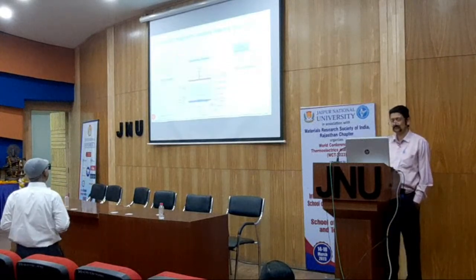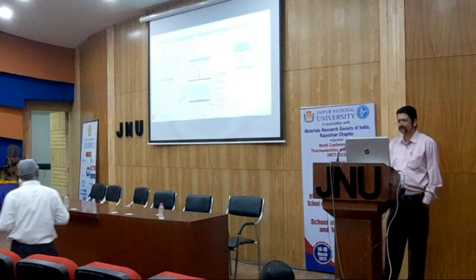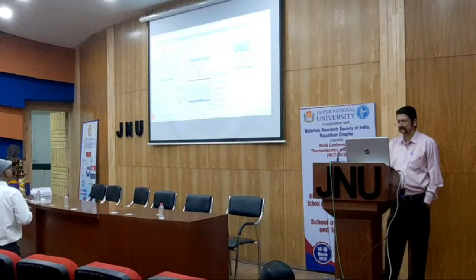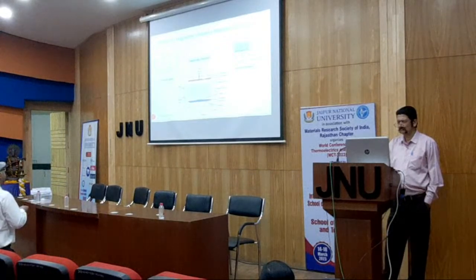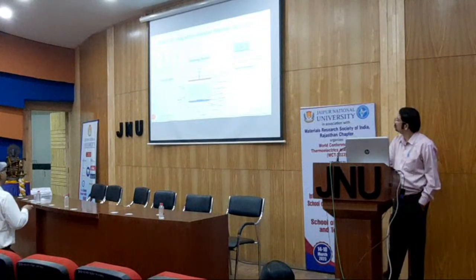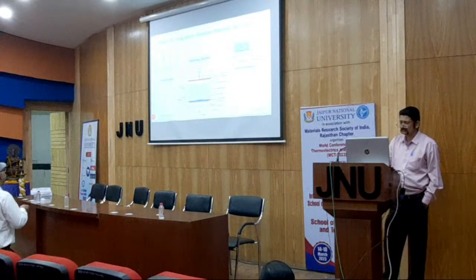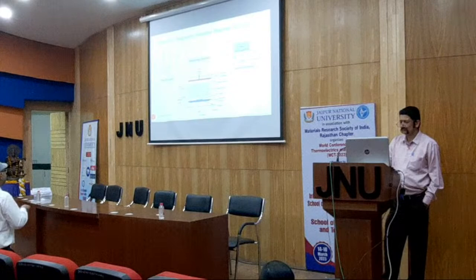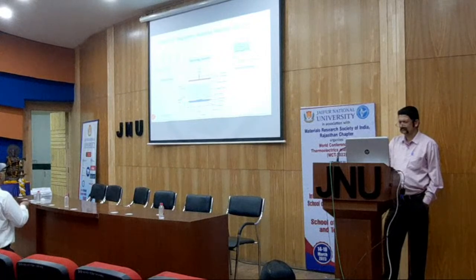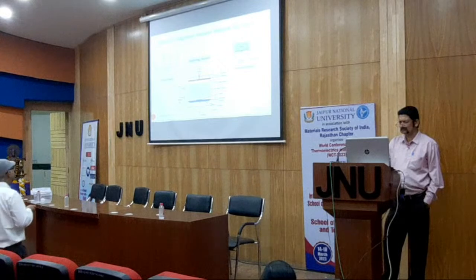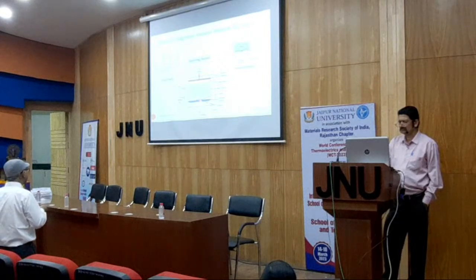Next please. Now you see how the equipment looks. We are applying these pulses at this electrode, which is like a cathode, where the target material, in our present case titanium, has been used. The plasma is created over here, and the wafer is placed over here, so that by reactive reaction, with the reactive gas which is nitrogen in this case, and argon as the bombardment or sputtering gas, the film is deposited over here.